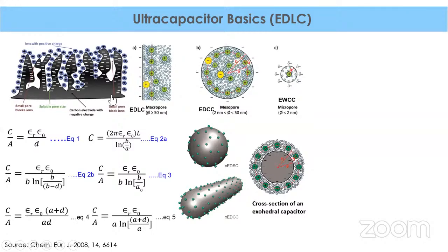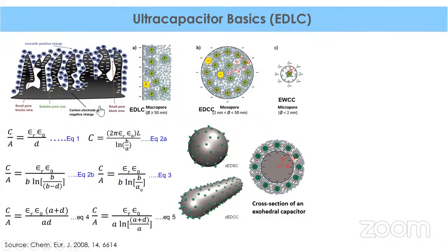But there was a group at Oak Ridge National Lab in the USA. They studied these porous carbon materials, and they came up with the hypothesis that this equation, which is used for a conventional capacitor, cannot be directly applied to understand the capacitance or the energy storage of EDLC. And that is the reason why these kinds of systems give higher capacitance than conventional capacitors. So it's not directly only related to surface area, even though surface area is one of the important parameters here as well.